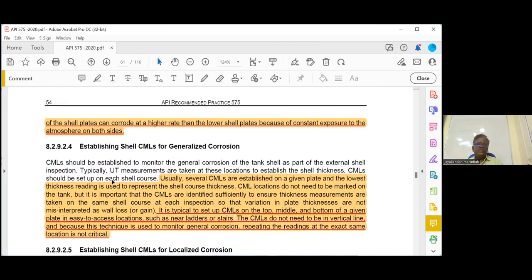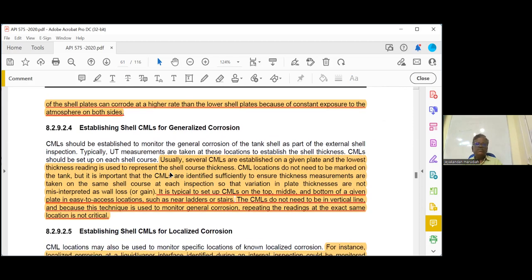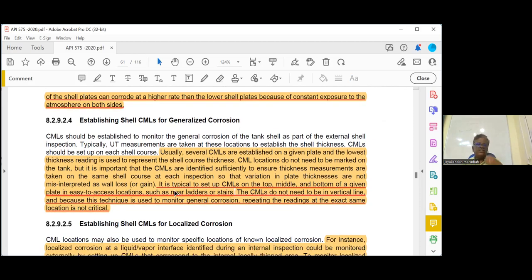Okay. Then establishing the shell CMLs for general corrosion, highlight the last 3 lines, 8.2.9.2.4. It is typical to set up CMLs on the top, middle, and the bottom of a given plate in easy to access locations such as near ladders or stairs. The CMLs do not need to be in a vertical line, and because this technique is used to monitor general corrosion, repeating the readings at the exact same location is not critical.